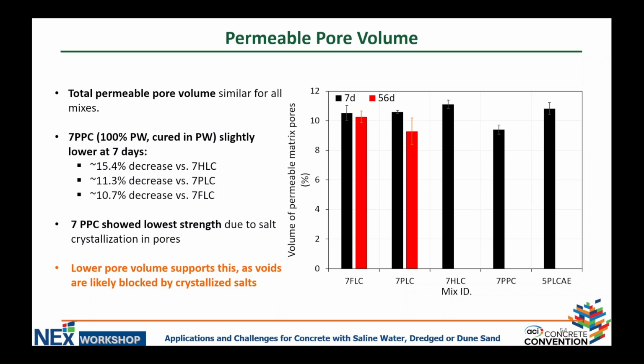And here comes the hypothesis we developed for what is happening here with curing and mixing with produced water. We believe that there is some sort of salt crystallization inside the pores of the 7PPC mix. That resulted in a decrease in the porosity, and also, because of the salt crystallization, it applied some internal stresses that decreased the compressive strength and also decreased the electrical resistivity. Again, this is the hypothesis we have at this point. It requires further testing to further enhance our view about that.